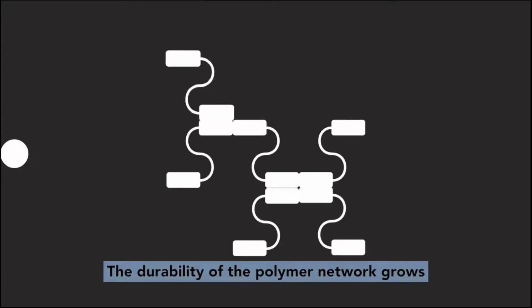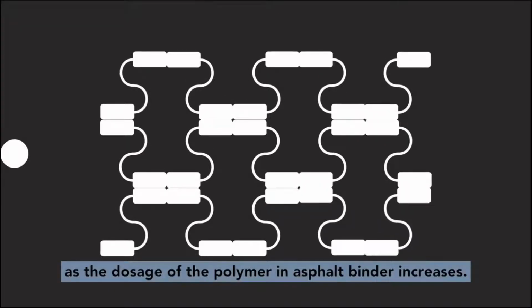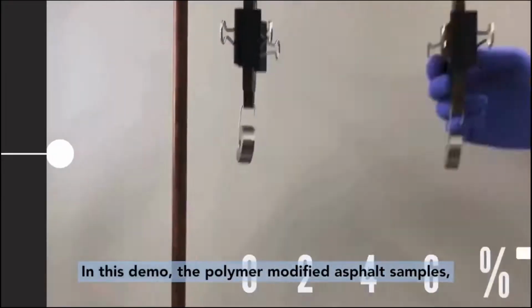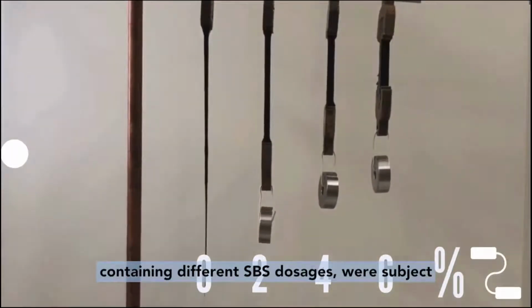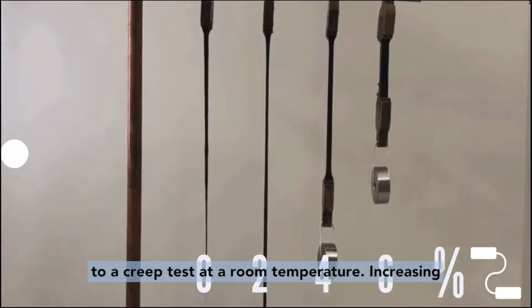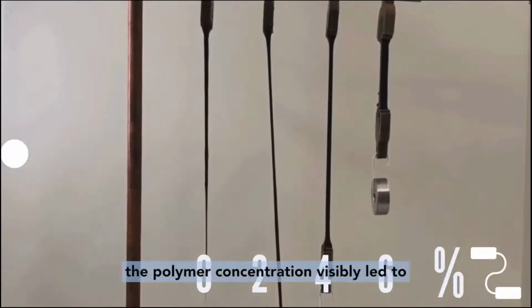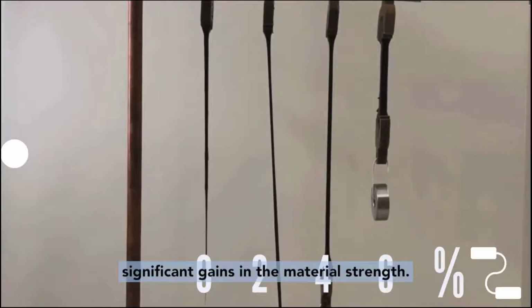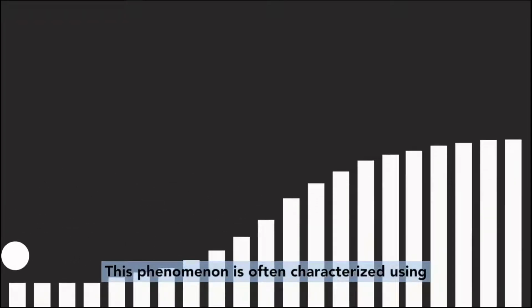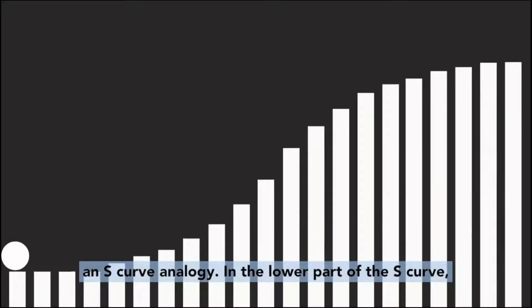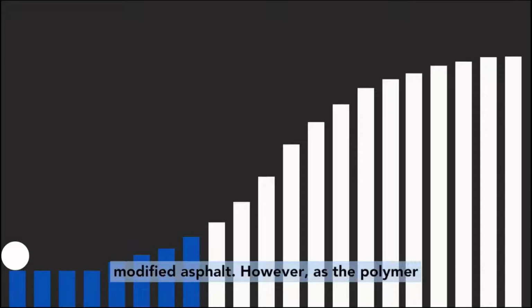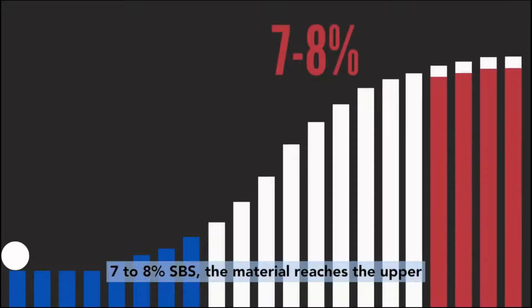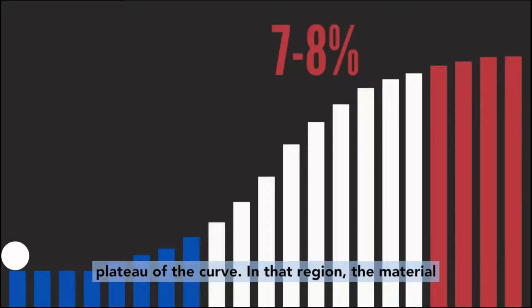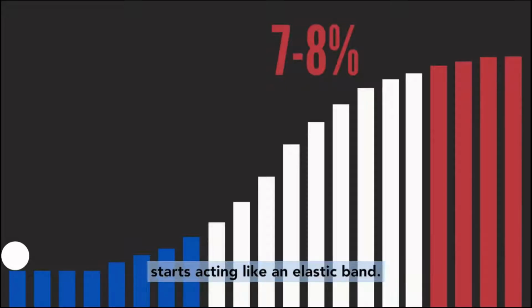The durability of the polymer network grows as the dosage of the polymer in asphalt binder increases. In this demo, the polymer modified asphalt samples containing different SBS dosages were subject to a creep test at room temperature. Increasing the polymer concentration visibly led to significant gains in the material strength. This phenomenon is often characterized using an S-curve analogy. In the lower part of the S-curve, the material acts as a traditional polymer modified asphalt. However, as the polymer concentration increases to approximately 7 to 8% SBS, the material reaches the upper plateau of the curve. In that region, the material starts acting like an elastic band.